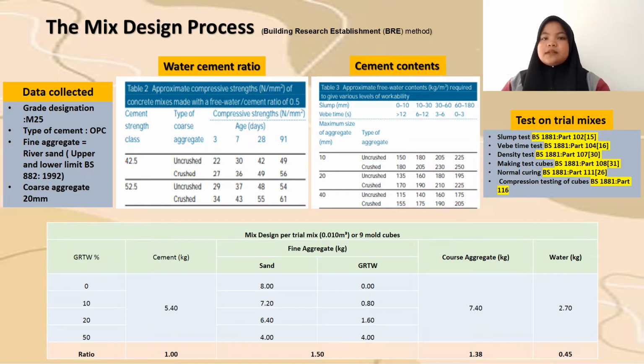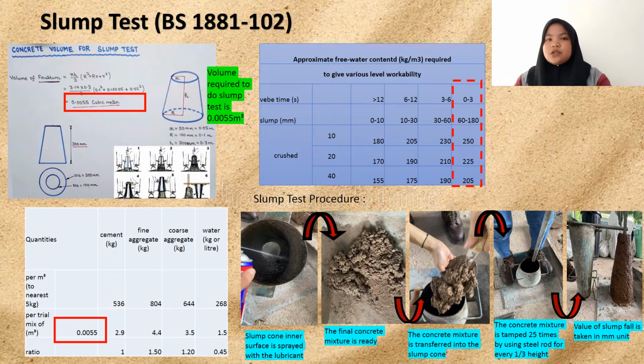Concrete cube is cast on site using M25 concrete grade, with a mixing ratio from the BRE method, which is 1 to 1.5 to 1.38 to 0.45 for cement, fine aggregate, coarse aggregate, and water. Slump tests were determined according to British standard shown in the table and focus on slump fall value 60 to 180. The volume of slump cone was calculated and the value is 0.0055 cubic metre. The volume used for each mixture of cement, fine aggregate, coarse aggregate, and water of the total quantity that used.